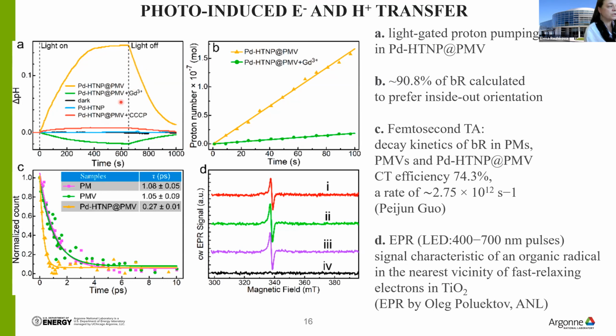It's important to show here that we utilized multiple controls. There is no reaction in dark. There is no reaction if you do not have proton pumps, but just inorganic particles. And there is no reaction if we use an organic inhibitor of proton transfer, CCCP. And also, it's known from literature that gadolinium salts, gadolinium complexes can actually block proton pumping only from the cytoplasmic side, from the negatively charged side of the membrane.